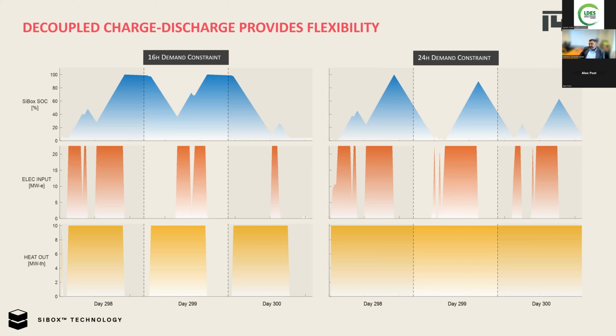Now, coming back to the simultaneous charge-discharge capability, if the customer demand requirement is for a 16-hour heat system or 24-hour constant heat supply, you don't need to design your storage with 16 or 24 hours of storage. It really depends on what the generation profile is and what the price fluctuation is if it is grid connected. The curves I've shown here are for an 8-hour discharge system, which can charge in 4 hours and supply heat for 16 hours in this case, and 24 hours in the case on the right-hand side, based on changing the charging profile of the system. This is run through an annual simulation, and is something that we will also demonstrate using our module. What makes it possible is the capability to simultaneously charge and discharge the system.